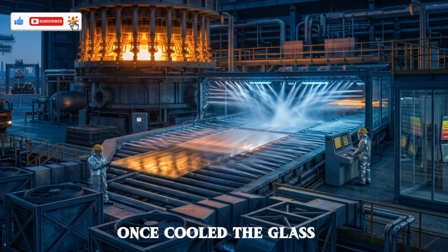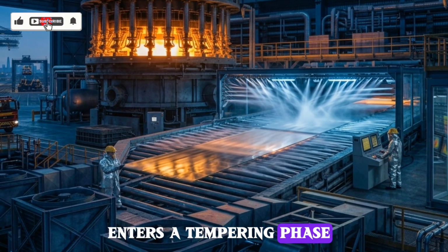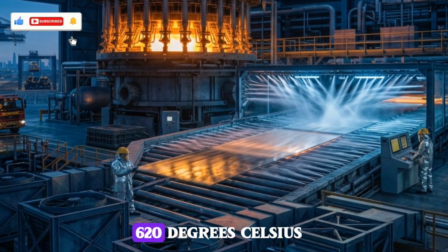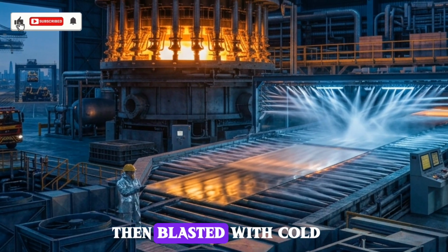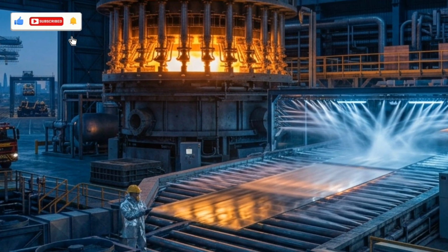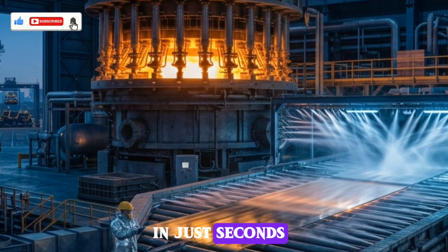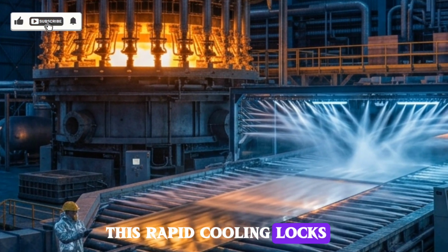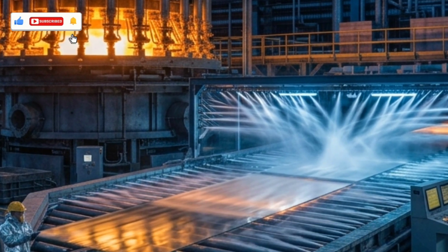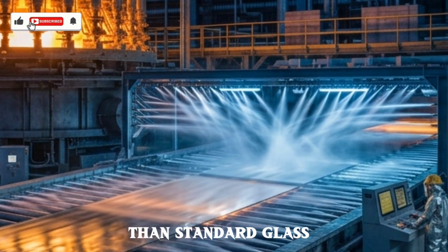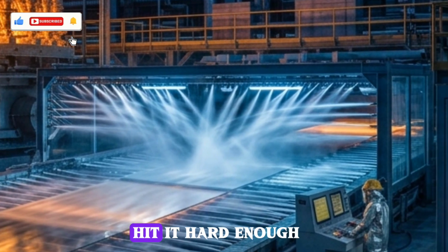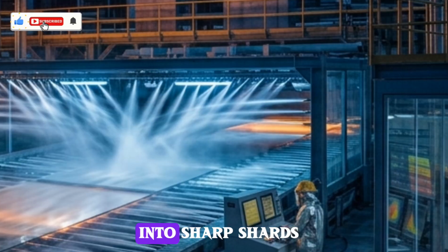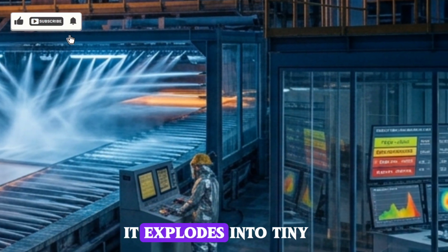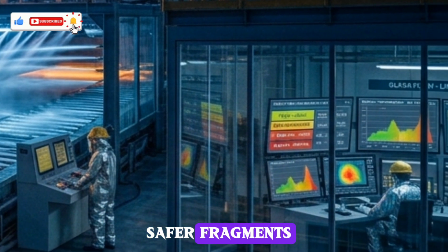Once cooled, the glass enters a tempering phase. It's reheated to around 620 degrees Celsius, then blasted with cold air at high pressure, up to 10 bar. In just seconds, this rapid cooling locks the outer surface into compression, making the glass up to 5 times stronger than standard glass. Hit it hard enough, and it won't shatter into sharp shards. It explodes into tiny, safer fragments.